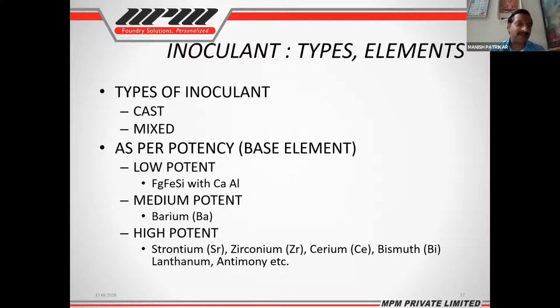So low potent is a ferrosilicon with calcium and aluminum. Actually, all inoculants have ferrosilicon with calcium and aluminum. Then medium potent is a barium-based inoculant. High potent is the strontium, zirconium, cerium, bismuth, lanthanum, antimony, because these are very specific and very strong inoculants where you need a specific purpose to use them. Otherwise, even an extra dose of these inoculants will give you a defect.